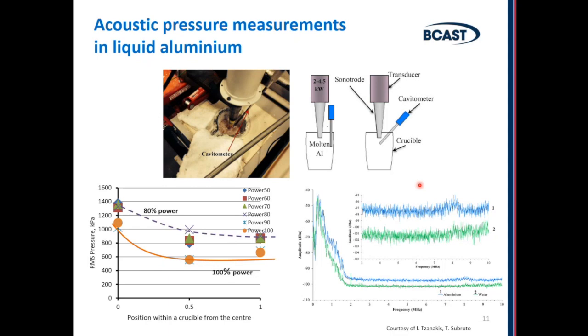We could, for a long time, do it in low temperature liquids like water, since the 1950s. But nowadays we can also do it in liquid aluminium using metallic probes. This is an example of such a measurement showing that you have attenuation of pressure in liquids. Moving from the tip of the probe or sonotrode to the side, you will have attenuation of the pressure. But also you can see that it's not necessarily that 100% power, so maximum amplitude of vibrations, is better than smaller amplitude of vibrations.